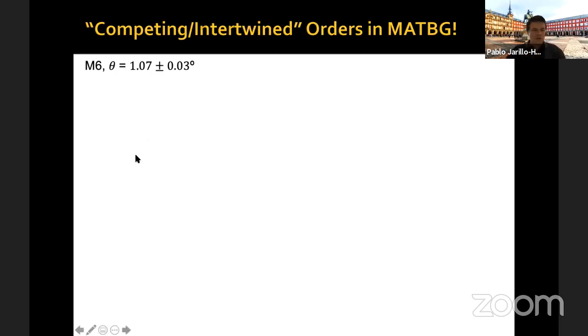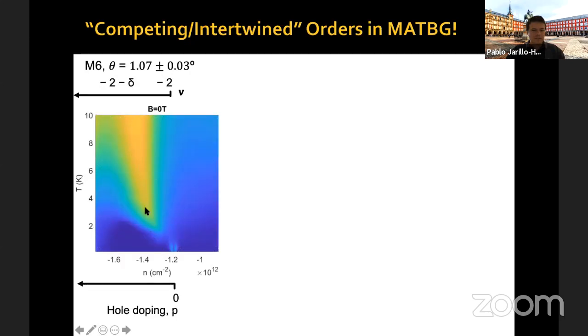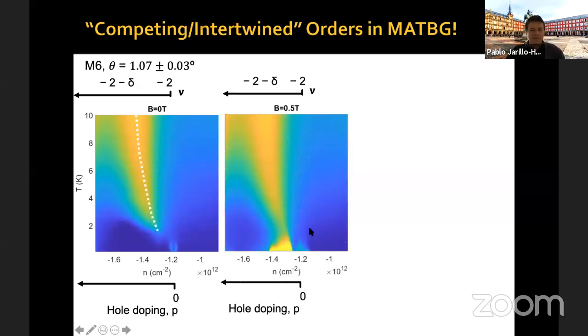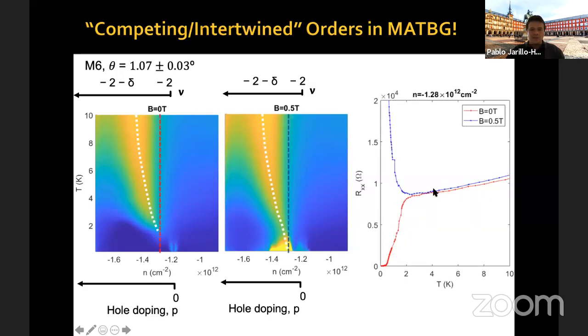So we have another device here. You see again this prominent wedge. In this case, there is also a pretty weak correlated insulator state at 2 holes per moiré unit cell. There is a depletion of TC here. And when you apply a finite magnetic field, you can see that this leads to an insulating state, in this case separated from the original correlated insulator state, which becomes a bit stronger at finite magnetic field. And again, if you take traces at those locations, you see superconductivity and the insulating state, which happens at finite magnetic field.